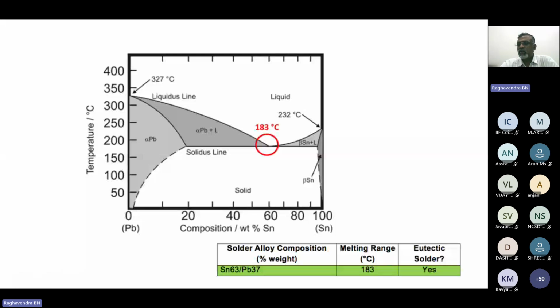Say for example, you are into this line, and one of your customers asks, I need a solder alloy, but it should have a higher melting point for a particular application, say around 200 degrees centigrade. So then what do we need to do? Increase the tin, reduce the lead. Either way, basically by the phase diagram we need to shift to here, say around 200. So you will know what is the percentage of lead and tin. That is the advantage of understanding the phase diagram.